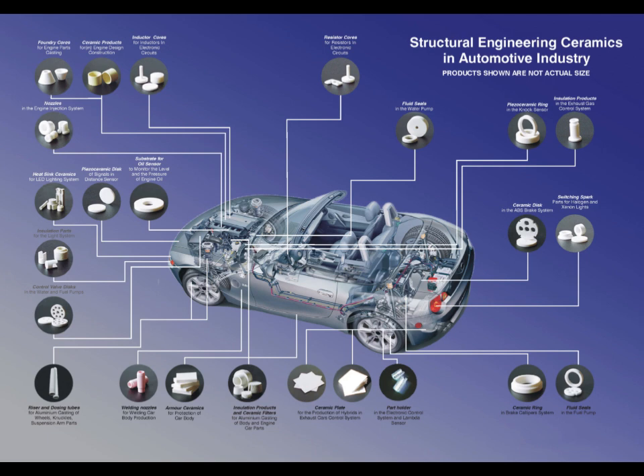For injection molding, the silicon nitride powder is mixed with alumina and yttrium oxide to get the properties needed for the part. Then you form your feedstock, which is a mixture of organic additives needed like your binders, plasticizers, dispersants, and lubricants. Once that is made, you mix them and inject them into a heated mold. At this point it has formed the green part, and is subsequently heated to burn off the binder, and finally sintered to a dense final component.